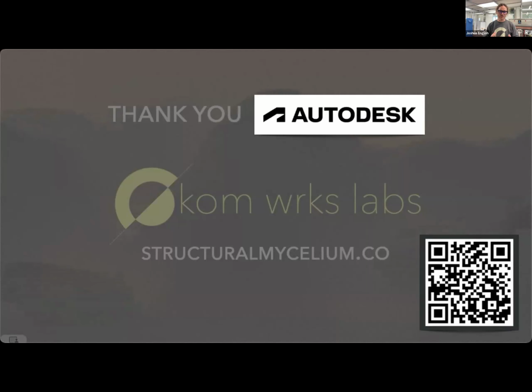As I mentioned, when fungi are alive, they can become hydrophobic or hydrophilic depending on what the organism needs at the time. When it becomes hydrophobic, it's alive and well, and it's full of water, and it's happy and doing its thing. But when it needs to rest because conditions aren't right, it'll dry itself out a little bit, and that's when it becomes hydrophilic, so that when conditions improve, it can absorb that water again and continue to grow. But what we found is that at the end of the growth process, when we finish that drying process, that amphipathic pathway, as it's called, where it can switch to both sides, is now cut off because the organism is no longer alive.